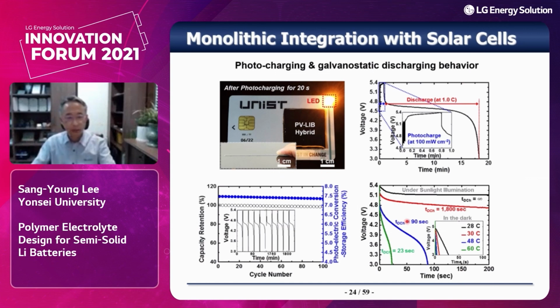Okay, and then the normal photocharging and galvanostatic discharge behavior was observed. One interesting finding is what our hybrid cell can provide under sunlight illumination. Please take a look at this red line. This is a discharge profile at a discharge current density of 1.0 C. With this significantly high current density, there is no significant drop in voltage, thanks to the combination with the solar cell. This is one advantage of a hybrid concept.